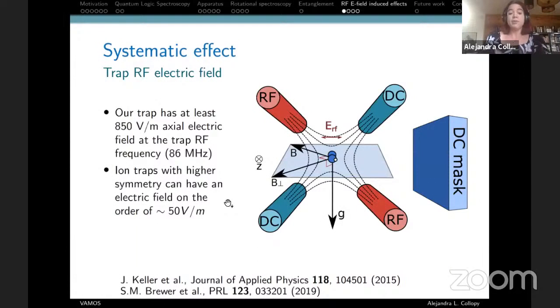I'm going to finish up this talk by talking about a systematic effect that we've been looking into recently, which is that due to the RF electric field experienced by the ion in the trap. So in a perfect world, if you had infinitely long electrodes, you would be able to apply compensation voltages to your DC electrodes in such a way that you could park yourself at the RF null, and the ion would experience no RF electric field at all. However, we do not have a perfect trap, and it wasn't really designed with high symmetry. And so even when we do our best job of compensation, we have at least 850 volts per meter of axial RF electric field at the trap RF drive frequency of 86 megahertz.